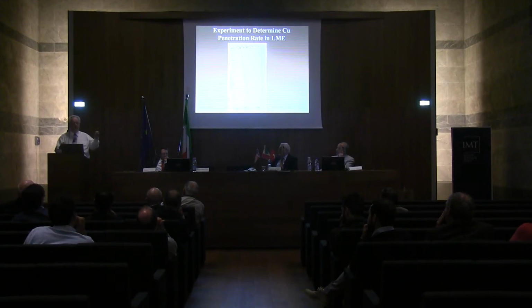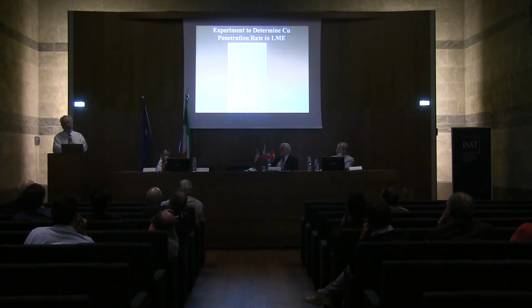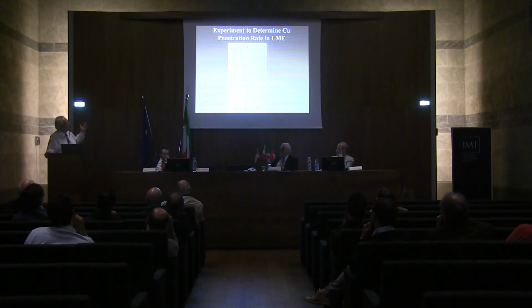And I tested one bar first with no copper on it at 1100 centigrade, which is the temperature that you could probably get to in these failures. And it's well below the melting point of the steel, but it's above the melting point of copper. So that took like 589 pounds to break at 1100 C. And then we tested at various amounts of load, less than 589. And I measured the crack growth rate on these samples. And you can see the plot here is a beautiful correlation when we look at a log-log plot. So when we published these results, again, the case was thrown out by the court.